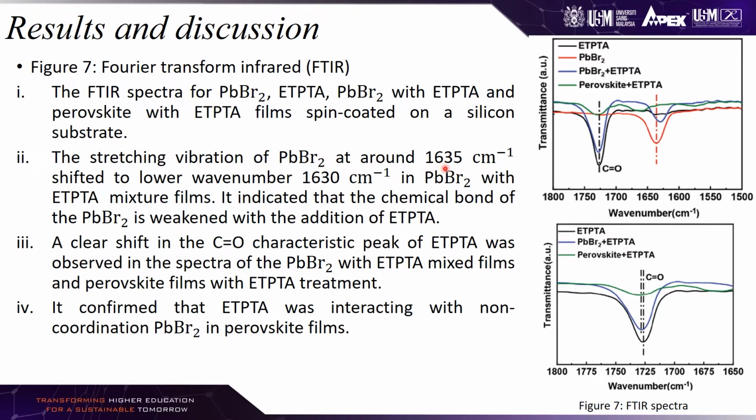The stretching vibration of PbBr2 at around 1635 centimeter^-1 shifted to a lower wave number 1630 centimeter^-1 in the PbBr2 with ETPTA mixture film.